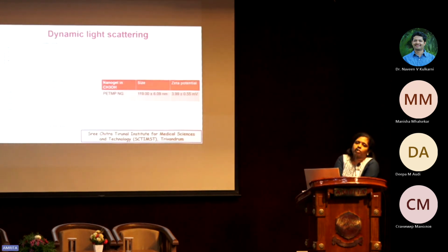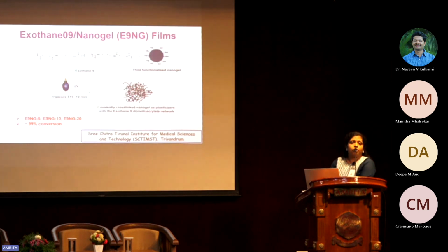We also checked the particle size and zeta potential of the nanogel to see how it is after the synthesis. And we got a size distribution of 190 nanometer and a zeta potential value of around 4 millivolt. So once we confirmed the thiol functionality of the nanogel and the spherical structure and the size, we incorporated this particular nanogel into the Exothane matrix at different weight percentages, and we used a photo curing technique to make the film in the presence of Irgacure, that is a photo catalyst.